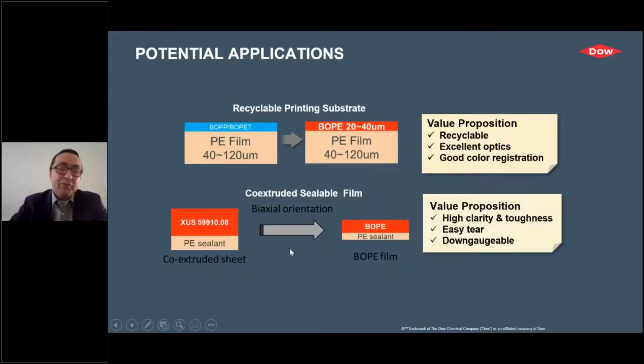The idea here is to use films based on this polymer in a multi-layer but monomaterial film and replace existing multi-material multi-layer films that contain polypropylene or polyester or polyamide together with polyethylene, which are very difficult to recycle. And this resulting film is very easy to recycle because it's one material, it's polyethylene. So it's recyclable, has excellent optics, very good clarity, easy tear, and is also down-gaugeable. And we can use that for printing substrates or for sealable film substrates.